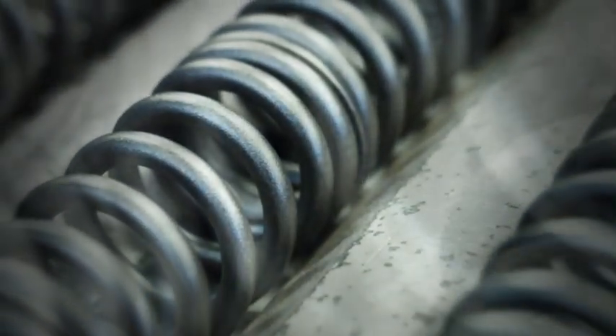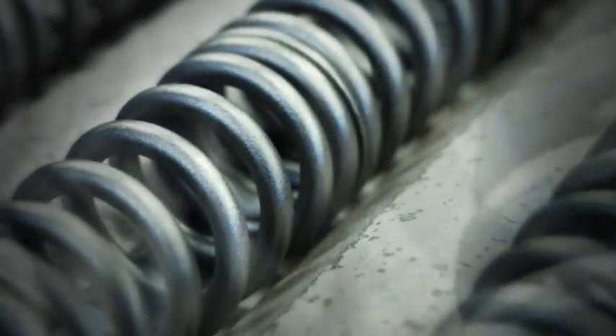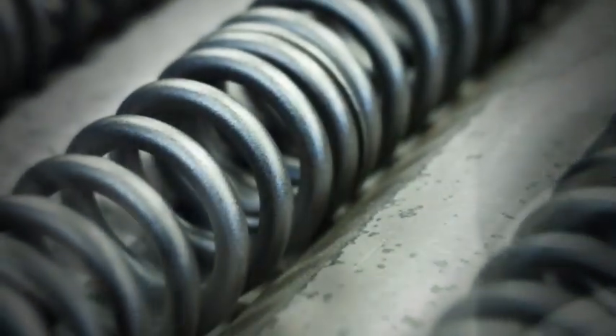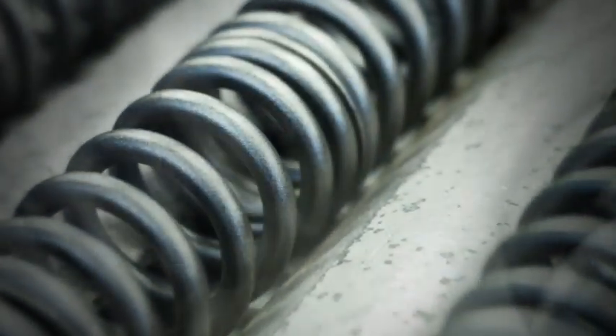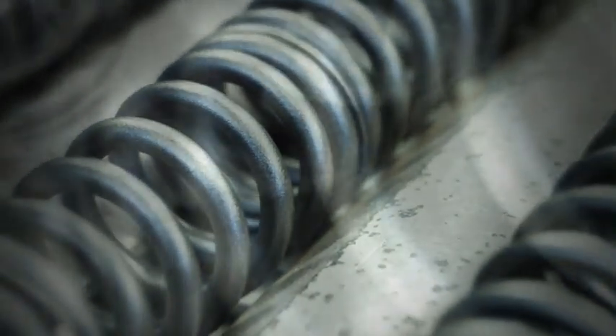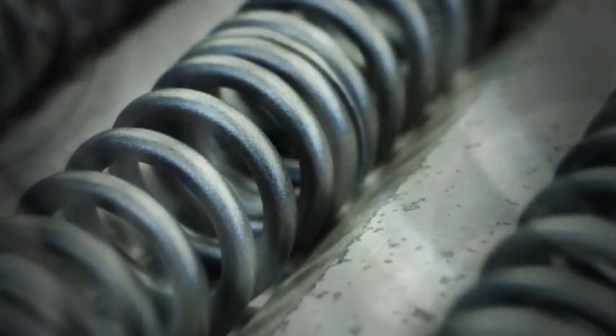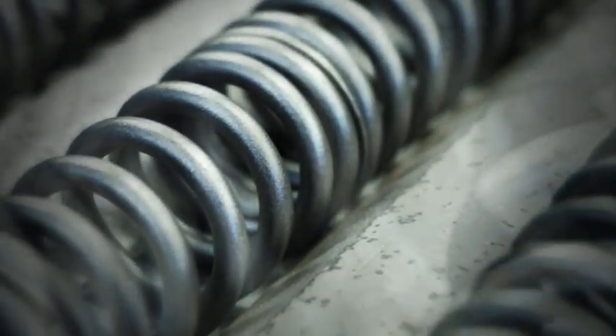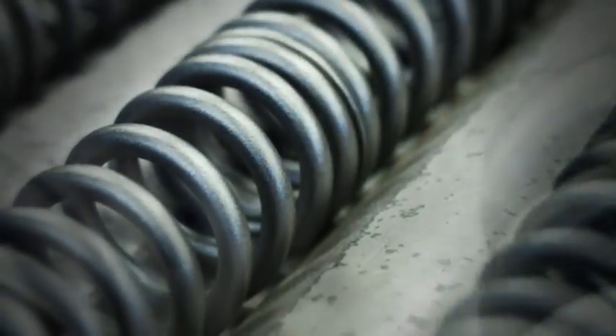Coverage, intensity, media condition, and access must be controlled. A region hidden from the shot may receive less benefit. Broken or contaminated media can damage the surface. Peening cannot repair a deep seam, poor heat treatment, or incorrect design. When performed correctly, it can greatly improve the fatigue resistance of highly stressed springs. Valve springs, suspension springs, and other dynamic components often receive carefully specified peening.